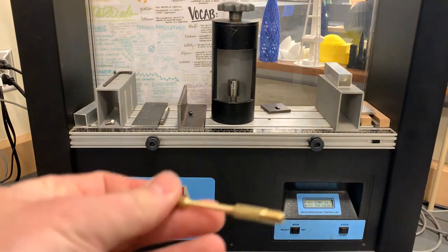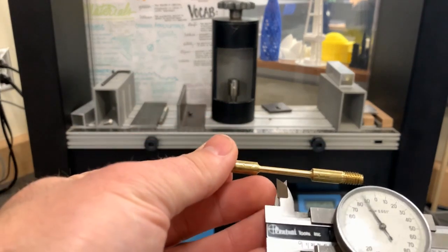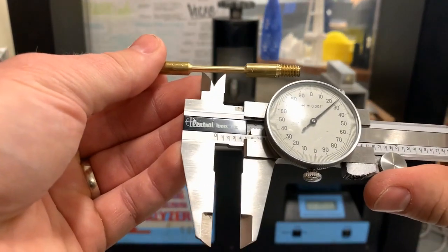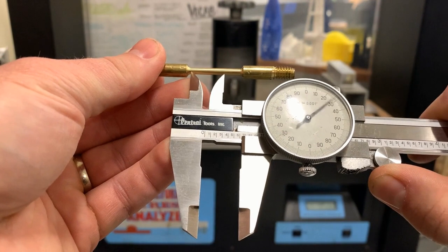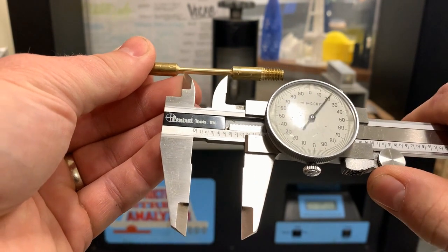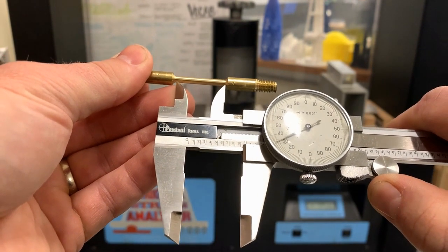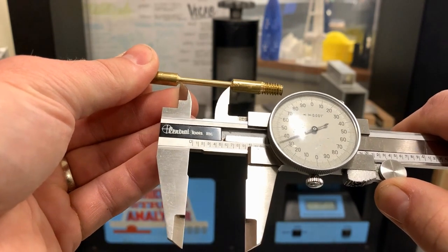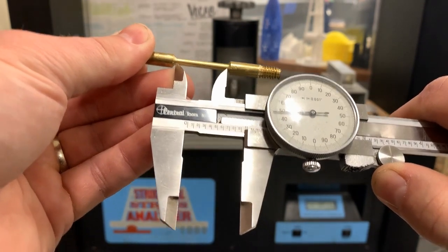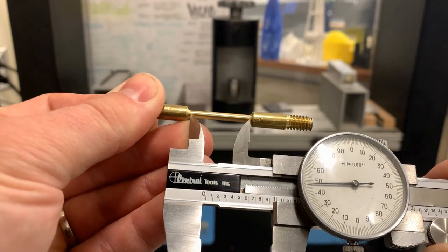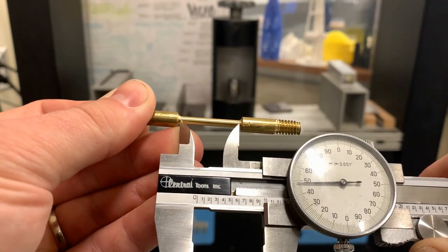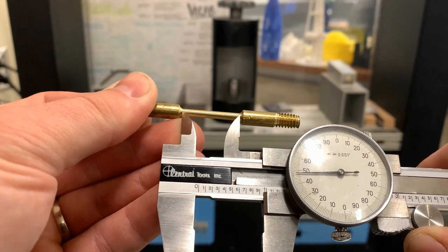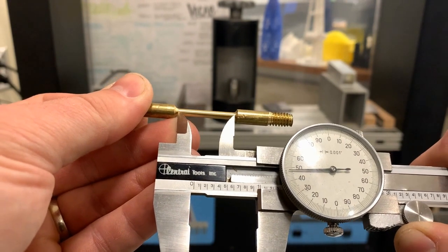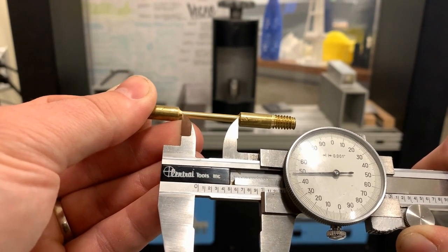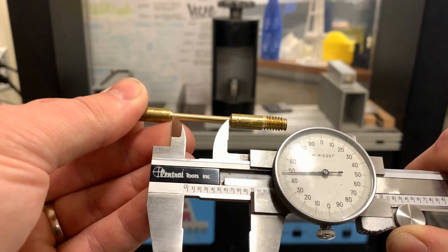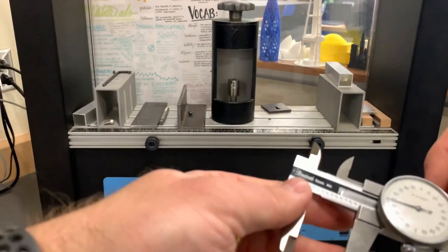Record that on your lab sheet. And then for the length, we need to use the little jaws on the caliper, and measure the length of the straight portion before it starts to curve out. So we don't want to capture that little radius that happens in there. We want to capture the straight portion. It's a little bit of a tricky measurement to take, but try your best. This is not actually exactly 1 inch. I'm a little bit short of that. It's about 0.95. That's the number I'm going to use for my strain calculation.